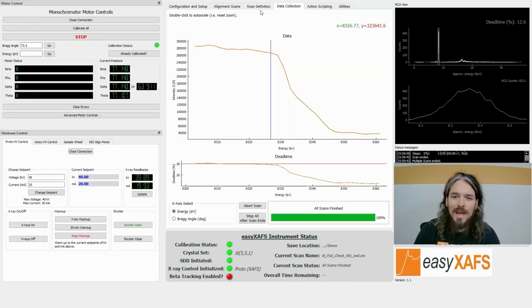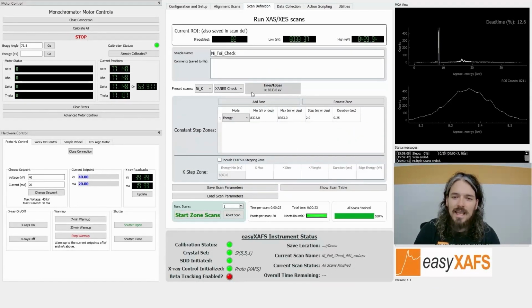Now I could go back to the scan definition tab, and if I change the preset scan type to XAFS, you can see that gives us 3 scan zones. We would have coarser steps in the pre-edge region, finer steps around the edge with a longer measurement time, and then coarse steps after the edge region. The default is around 15 minutes, but we've got some good samples here and we've got the system optimized, so we're going to be able to do the demonstration measurements with just 1.5 minutes per sample.